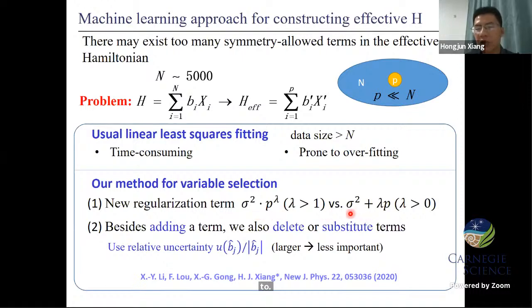So this is the usual regularization term, the lambda p term. The p means the number of interactions in this model, and this is sigma square, which means the variance of the fitting. So we are trying to fit to minimize these terms. A good model will minimize the difference between the DFT and the model, and at the same time it will minimize the number of parameters.